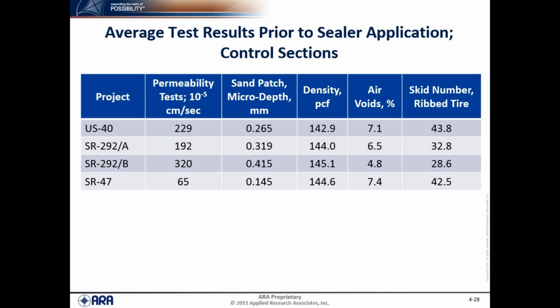Densities were reasonable. The US 40 had the lowest density prior to sealer application of about 143 pounds per cubic foot. And then conversely, the SR 292B had the greatest density, 145 pounds per cubic foot.